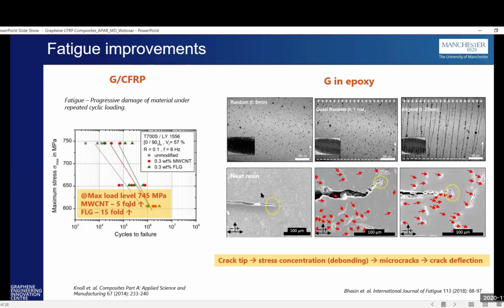For example, in the neat resin, if you look at the crack propagation, there's nothing in front of the crack to prevent it from going through, so it will eventually go to failure. Whereas with the randomly oriented graphene, because of the fatigue deformation, as I mentioned before, there's a stress concentration between the graphene and the matrix, which can create debonding and micro cracks. The crack propagates to these micro cracks, which means there is a crack deflection. Because of the crack deflection, it's absorbing more energy, and because of absorbing more energy, you're increasing the fatigue life of the material.